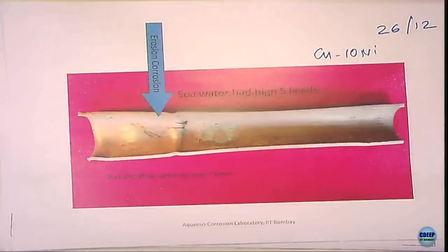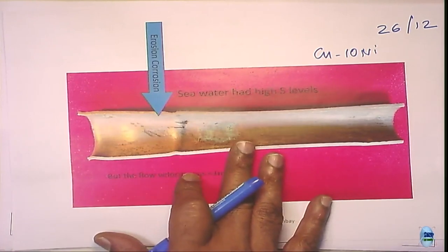The velocity is so low, look at this here, the velocity is 1 meter per second, then still why does it happen? We looked at the water, and it had a small amount of sand particles. So the critical velocity that you see from the textbook, which allows you to have about 2 meters per second, is no longer valid here.